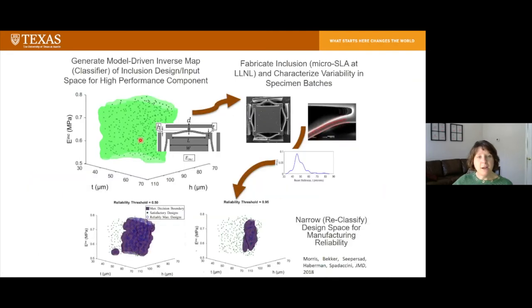So what we've done to combat that is we take our design space mapping. So this green cloud that you see here is the design region that indicates all of the high performing design points in terms of the thickness of the beams, the apex height of them, the modulus as well. Using the Livermore process, we're able to fabricate a batch of these inclusions.